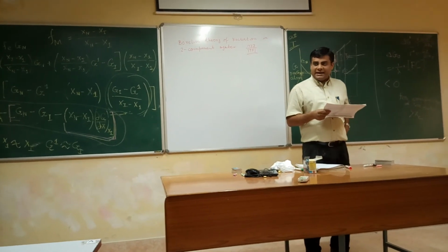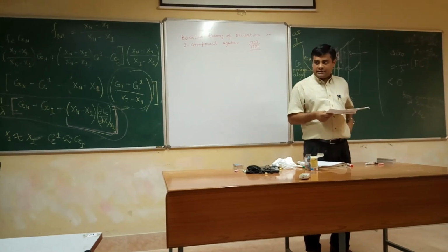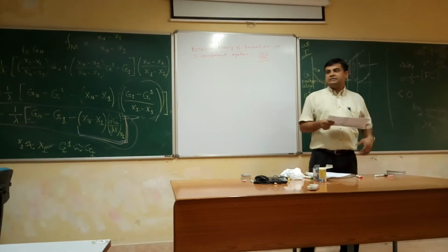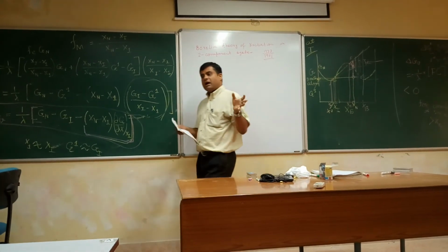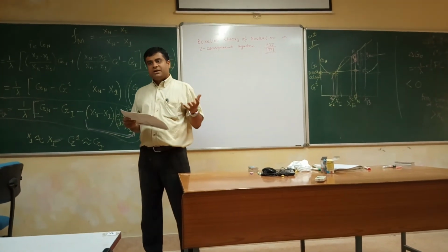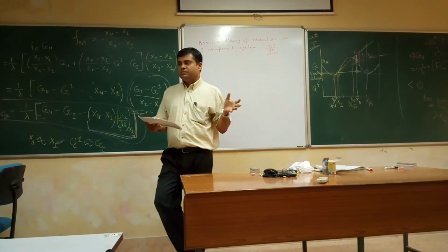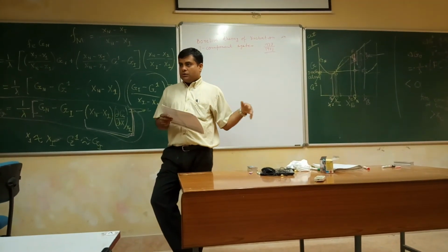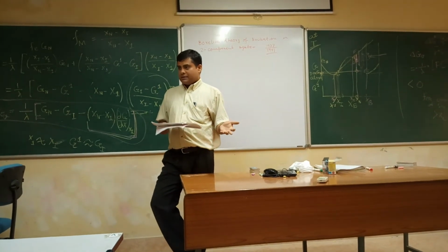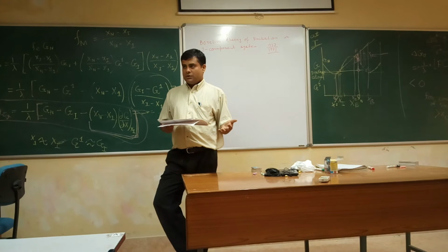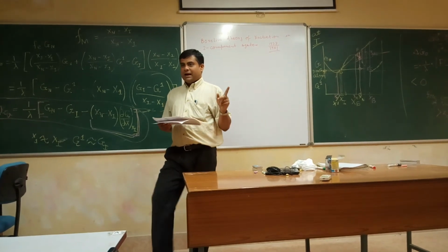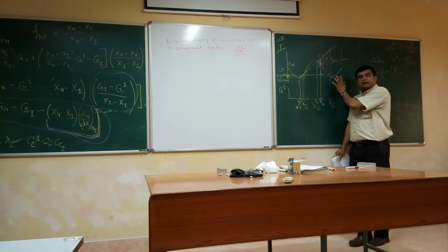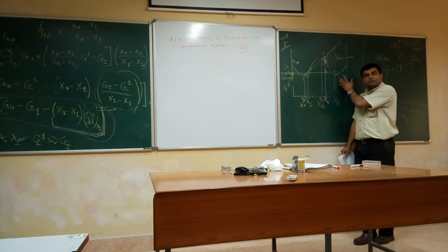So interfacial energy gamma is also neglected. Now the first one, fixed size fluctuation. Here he assumed that nuclei that are forming are of fixed size, say a certain number of atoms or a certain size, and for what composition nucleation is happening or the nucleation rate is maximum. So in Becker, even though he considered everything, ultimately he chose the embryo composition to be fixed at x beta.